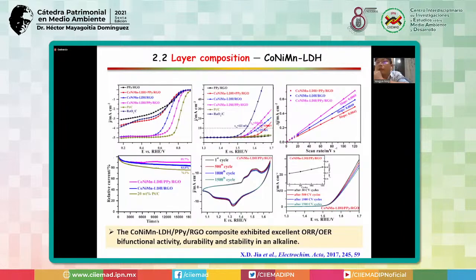So we also derived excellent bifunctional oxygen reduction reaction and oxygen evolution reaction activity, and also durability and stability in alkaline. Here we show about 18,000 seconds, with about 90% remaining, and also more than 1,500 CV cycles showing the stability.